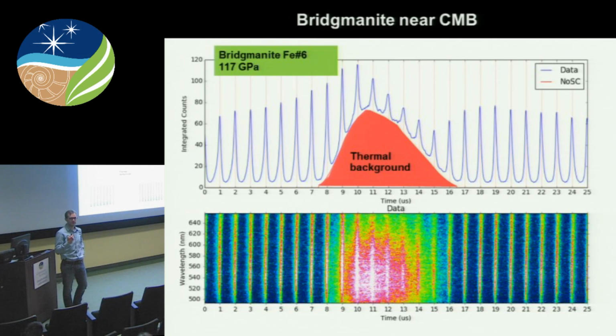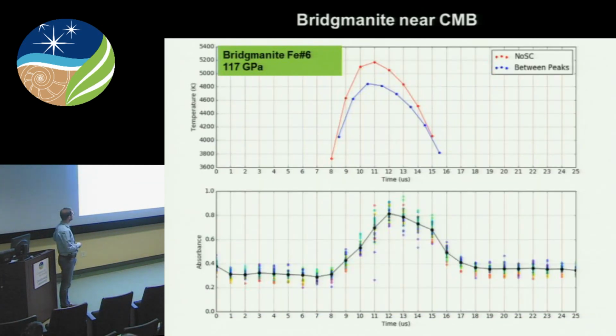So you can see that as your sample waits until the heating laser arrives around the 8th microsecond, the sample remains quite transparent. Then the thermal radiation shoots up, but your supercontinuum pulses obviously have a much weaker intensity now, which means that the sample is much darker at such high temperature conditions than it is at room temperature. And then you end up quenching your sample to a state that is more or less comparable to what you had before heating.